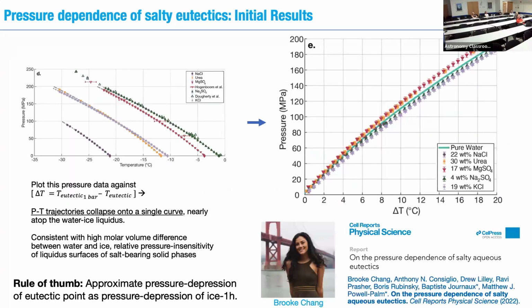So we then went to try and contextualize a little bit about these different pressure dependencies of the eutectic that we were seeing in these salt systems. So what I'm plotting here now is the eutectic pressure against the delta in temperature between the atmospheric pressure eutectic temperature and the temperature that we read, right? So you can think of this as the freezing point depression of the eutectic point.